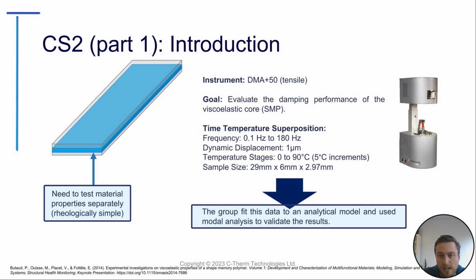They evaluated the damping performance of the viscoelastic core separately in tension with a DMA 50. The time temperature superposition was run from 0.1 hertz up to 180 hertz with a dynamic displacement of 1 micrometer, established to be in the linear range of deformation. They conducted this from 0 degrees up to 90 degrees with 5 degree increments for the temperature stages, using a sample 29 millimeters long, 6 millimeters wide, and 2.97 millimeters thick.